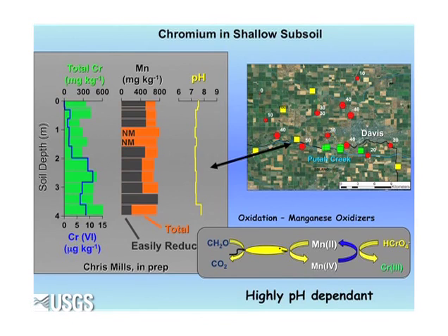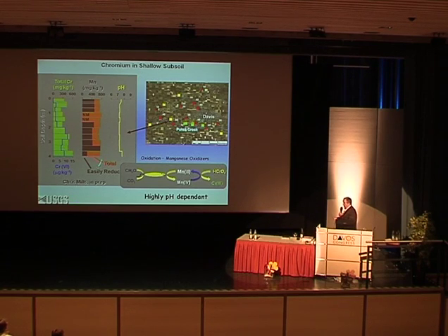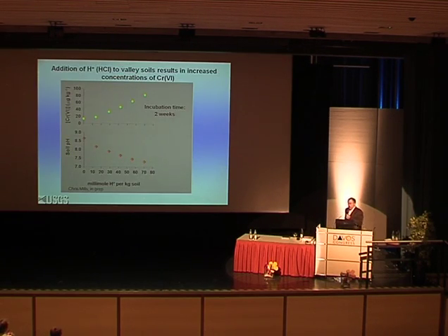Let me just go back one. A point I failed to make here is that Chris Mills, who's done a couple of years of experiments, and it's hard to show a couple of years of data with one slide, but basically what he's shown is that manganese is not limiting to this oxidation reaction. There's a lot of extra manganese, so some other factor is controlling the oxidation of chromium 3 to chromium 6.